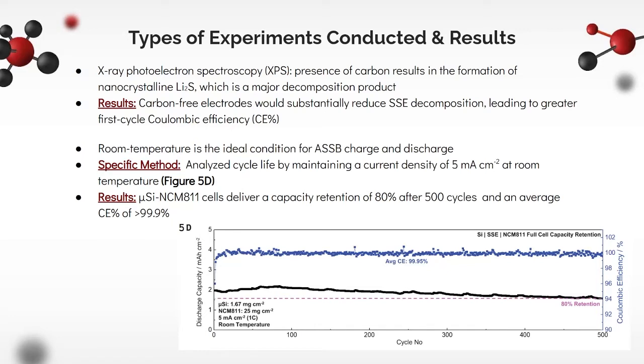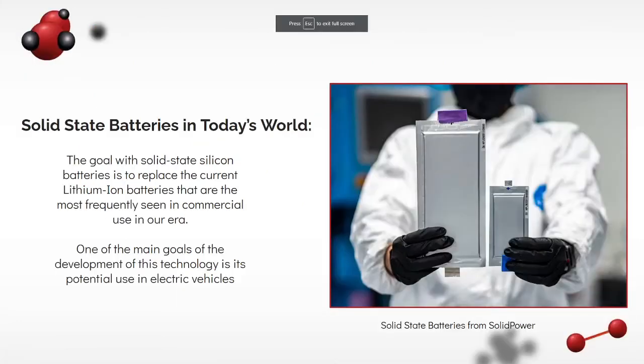As such, carbon-free electrodes would substantially reduce SSE decomposition, leading to greater first-cycle Coulombic efficiency. Also, room temperature is the ideal condition for ASSB charge and discharge. Researchers analyzed the cycle life by maintaining a current density of 5 milliamps per centimeter squared at room temperature as shown in Figure 5D. They found that micro-Si and NCM811 cells deliver a capacity retention of 80% after 500 cycles. Overall, the electrochemical results have reaffirmed the significant effectiveness of sulfide SSEs with microsilicon anodes.